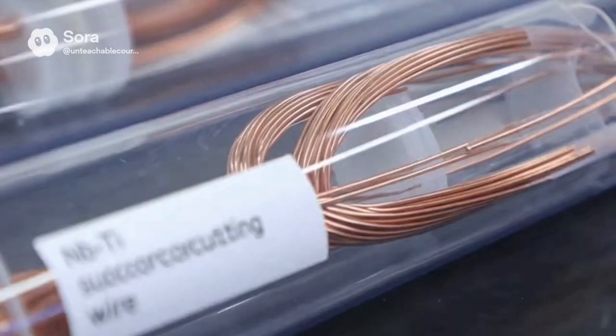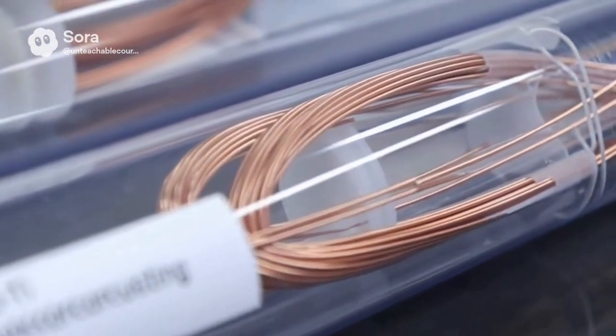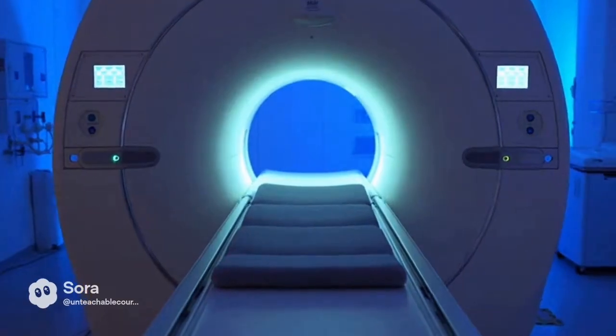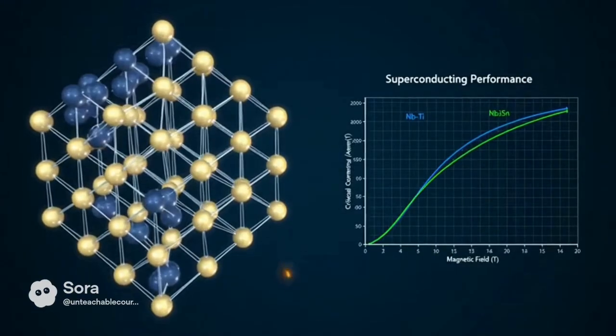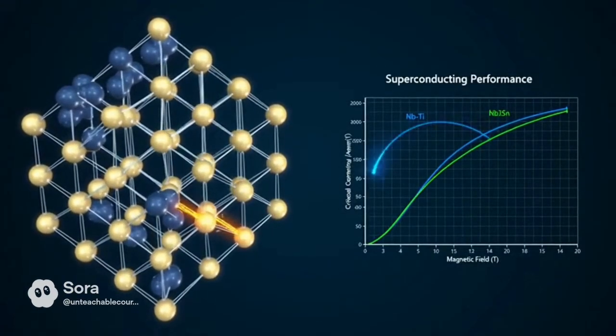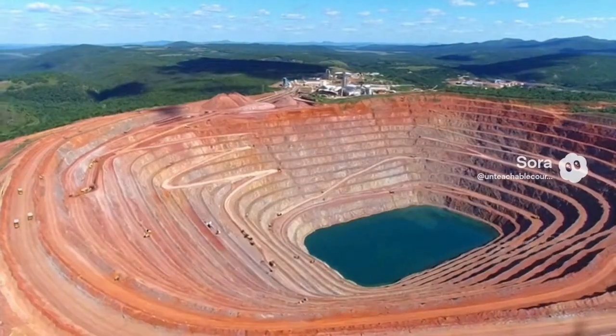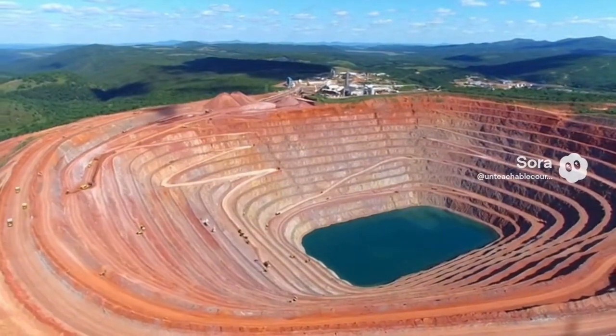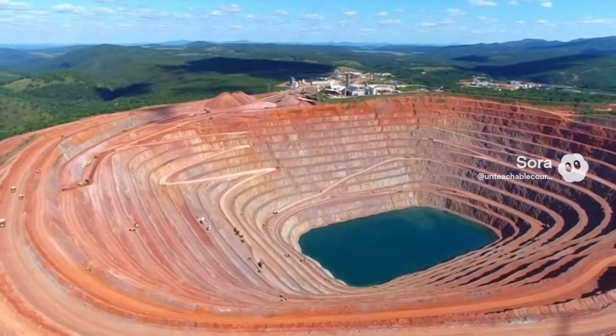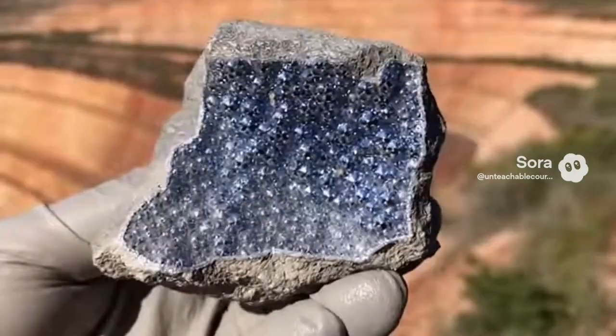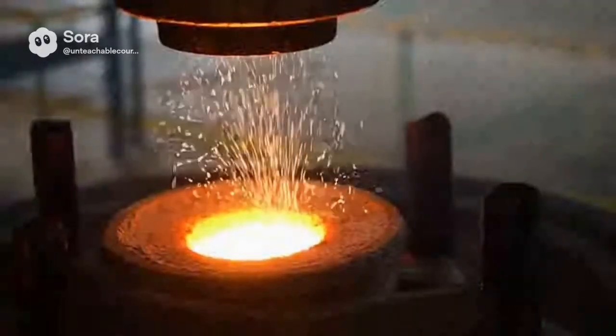Historically, niobium processing leaned on fluoride chemistry. Pyrochlore would be broken down with hydrofluoric acid, forming complex niobium fluorides that can be selectively separated from lookalike elements. Tantalum is the usual suspect, by solvent extraction. Modern flowsheets, as described by operators and patent literature, work hard to loop reagents and avoid open-ended acid consumption.